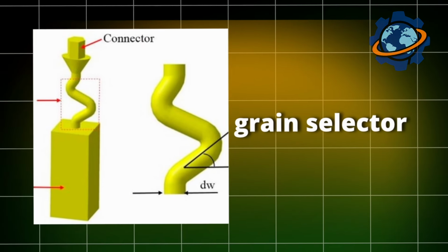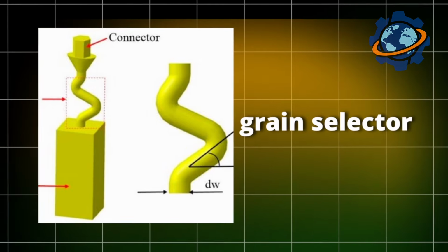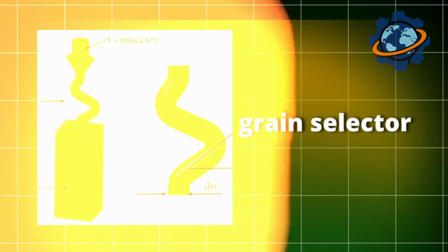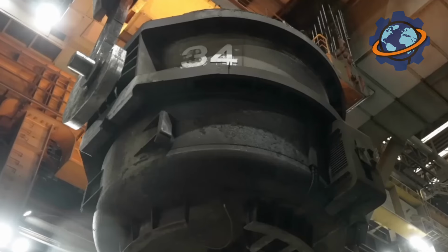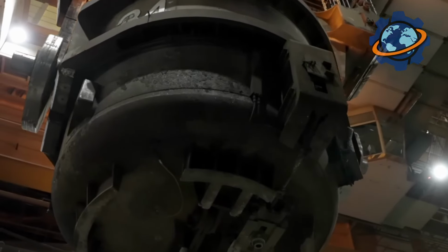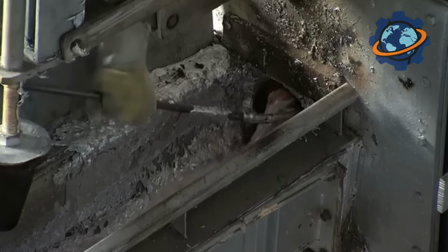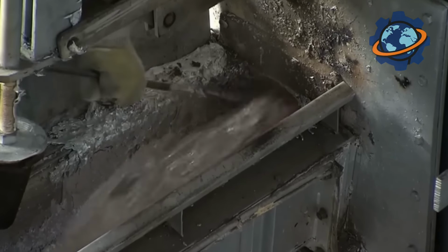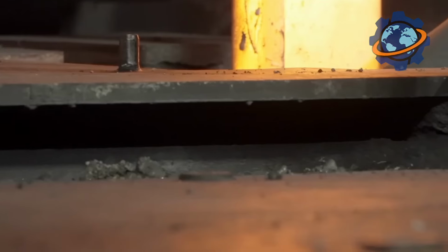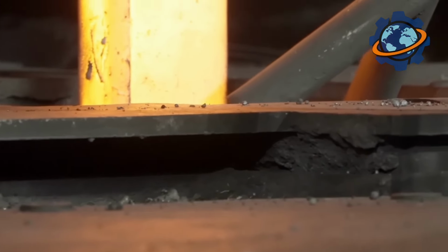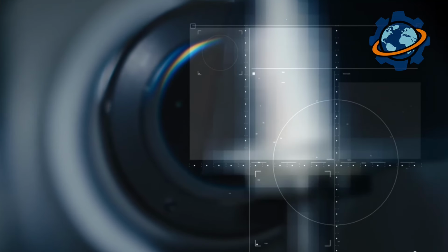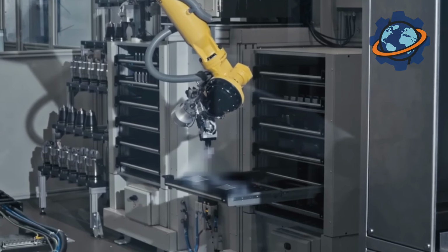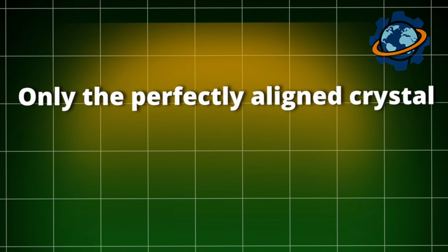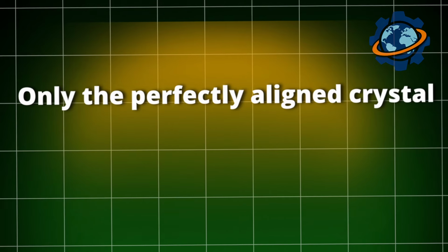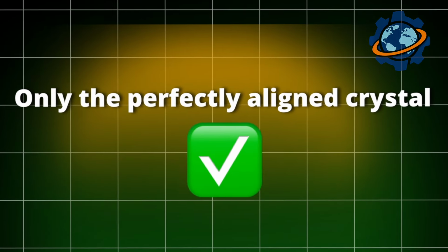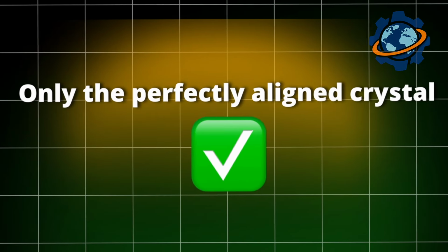But here's where physics becomes art. At the mold bottom sits a grain selector, a corkscrew-shaped passage so narrow only one crystal nucleus fits through. As metal solidifies upward, countless tiny crystals form at the chill plate. They compete, growing upward like metallic trees racing toward sunlight. Most hit the spiral walls and stop. Only the perfectly aligned crystal, the one matching the spiral's orientation, passes through this metallurgical gauntlet.